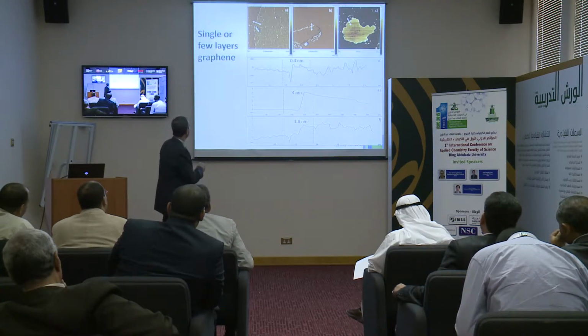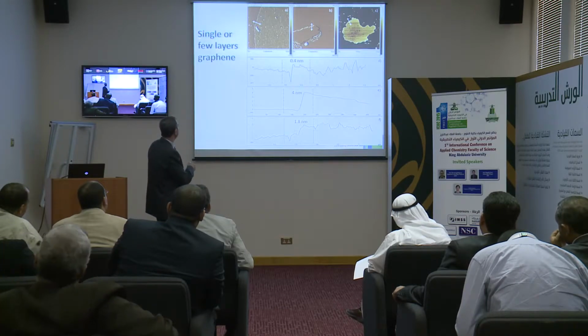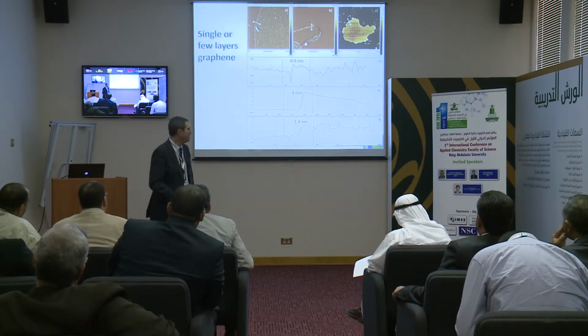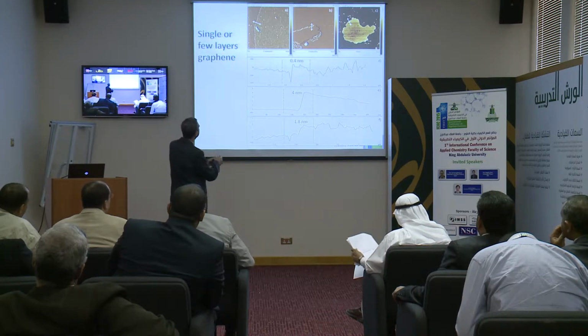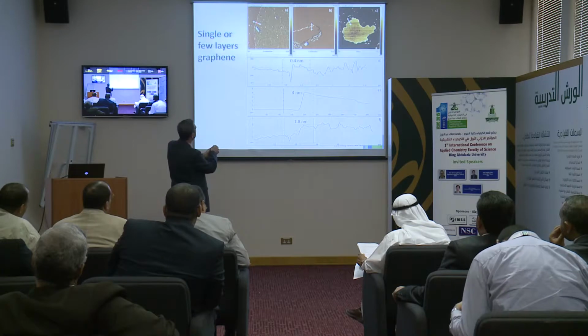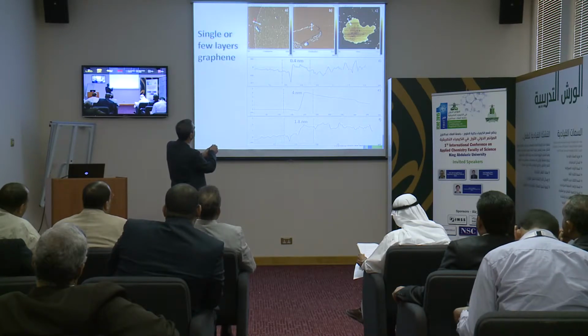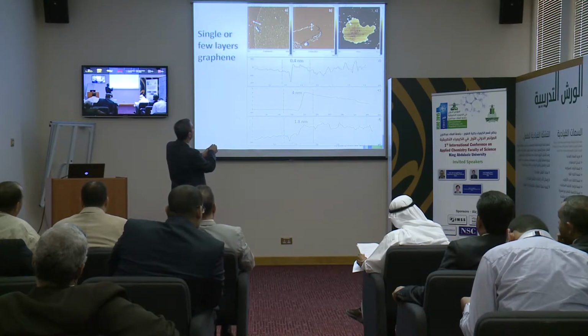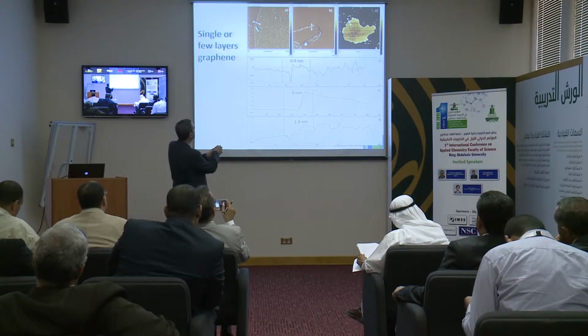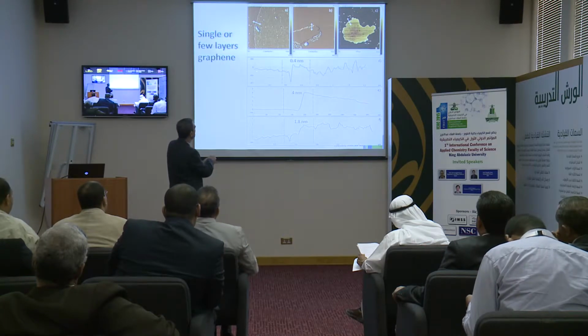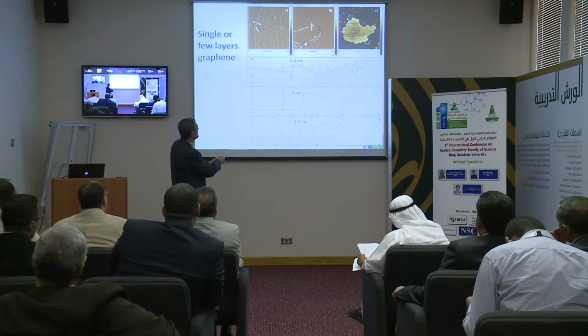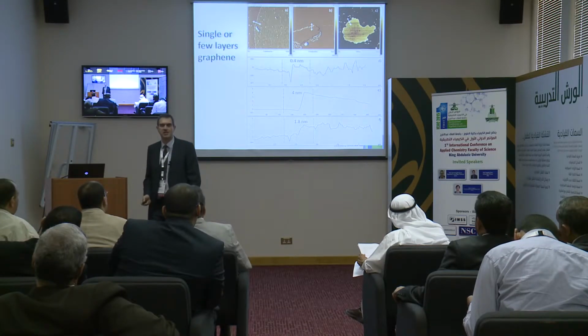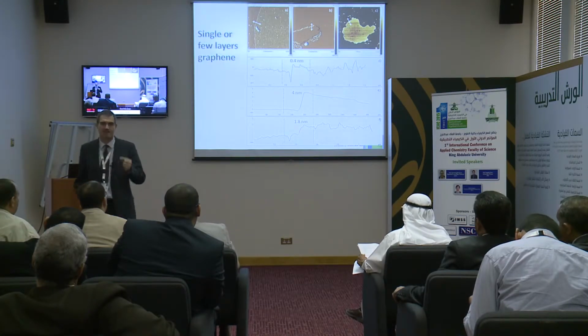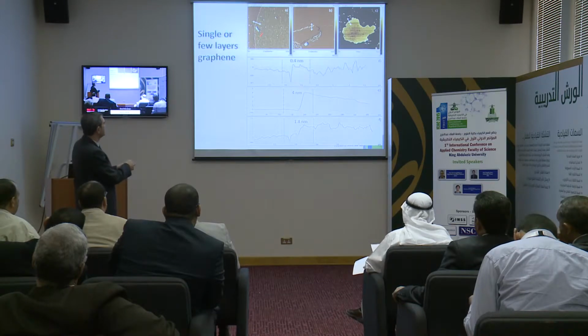Of course, whenever you want to prove that you can prepare single layer graphene, you have to do AFM. And in AFM, this is the frontal image of the material. And here we have a white line. This allows us to measure the difference in height between this point and this point. And in plot A, the difference in height is 0.4 nanometer. 0.4 nanometer is just the size that is expected for a graphene. So in this case, what we have is single layer graphene, but we can prepare also few layers graphene.